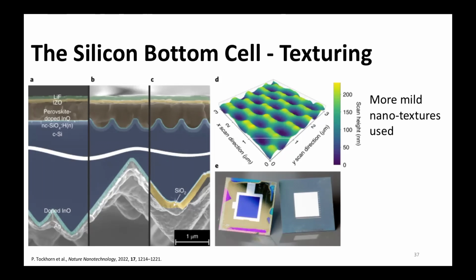So here we have nanotexturing. They have made a sinusoidal surface structure on the silicon, much smaller than these pyramids that are general in the silicon field. So only a couple hundred nanometers of this surface. So it is easier to deposit your perovskite layer. So we use nanotexturing. With lithography, we can make nanotextured silicon surfaces. We can control the dimensions, and that influences the interaction or the deposition of the perovskite. We have nanotextures. We can use them at both sides.